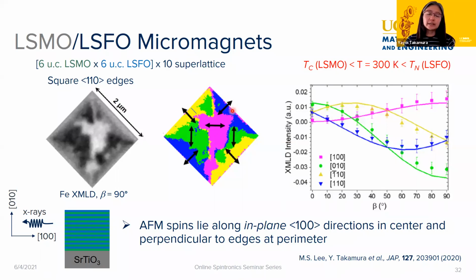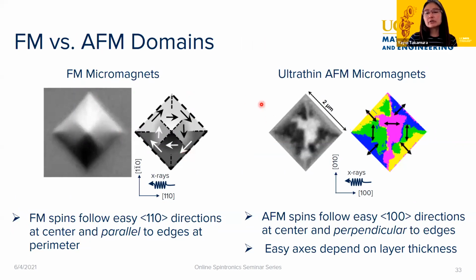Now again, these are completely in plane, but the antiferromagnetic spin axis wants to lie perpendicular to the edges of the nanostructures. If we compare what we are seeing for the ferromagnetic and antiferromagnetic domains, we see a similar effect: the center part wants to follow the orientation of our magnetocrystalline anisotropy, and then the edges will follow shape anisotropy. But for ferromagnetic materials, because we have magnetostatic energies, the perimeter wants to be parallel to the edges of the nanostructures. But in these ultra thin micromagnets, we are getting them to lie perpendicular to the edges, which is interesting. So again, this shows that we can use patterning as a way to dictate our antiferromagnetic spin axis orientations.